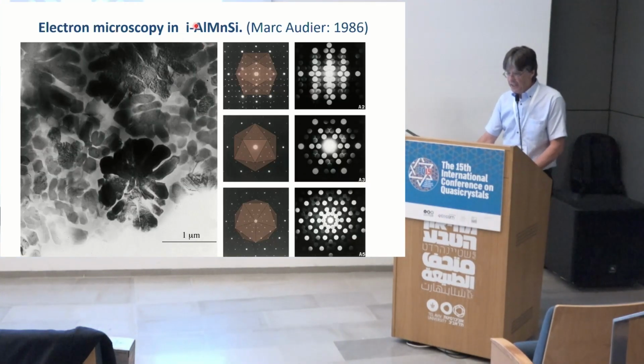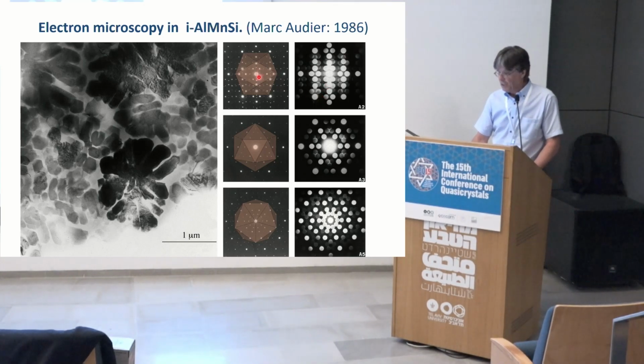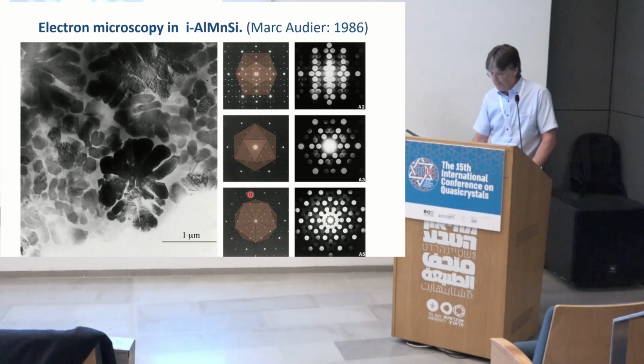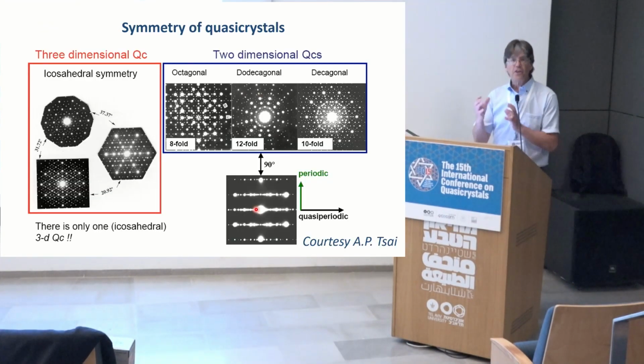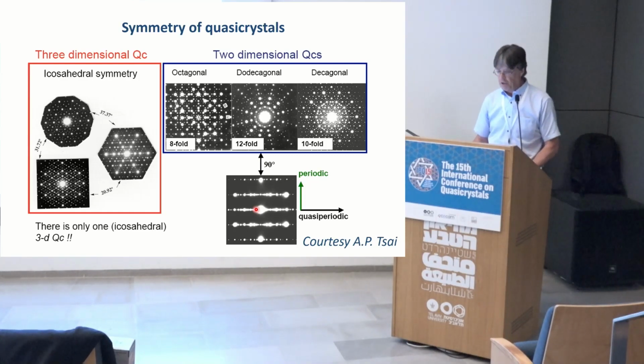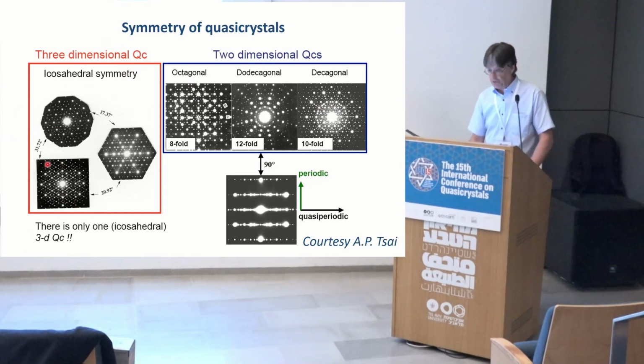And I'm taking here a nice electron microscopy image taken by Marc Audier, where you clearly see the twofold diffraction pattern here, the threefold symmetry here, and the fivefold symmetry or tenfold symmetry because of Friedel's law here. So it's really icosahedral symmetry. That's not the only one that is possible. There are many other possibilities. Icosahedral symmetry is the only one which is really a three-dimensional quasicrystal. And we have other quasicrystals where we have periodicity in one direction and quasi-periodicity perpendicular to this direction: octagonal, dodecagonal, and decagonal. I will concentrate in the following on this icosahedral symmetry.